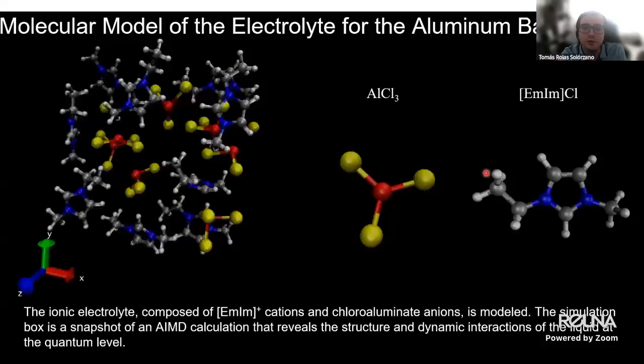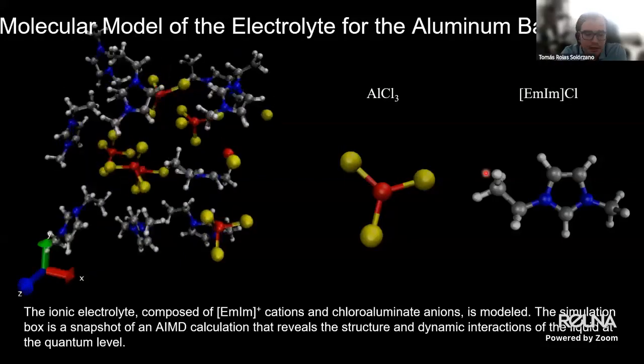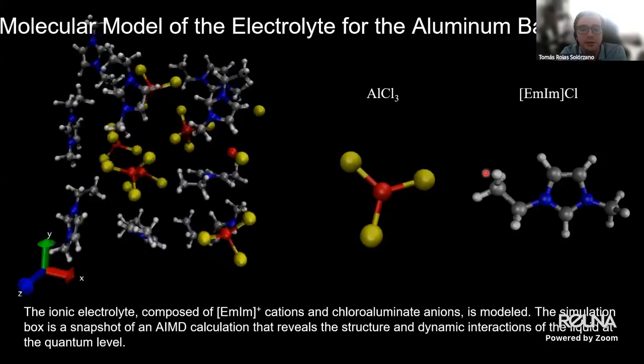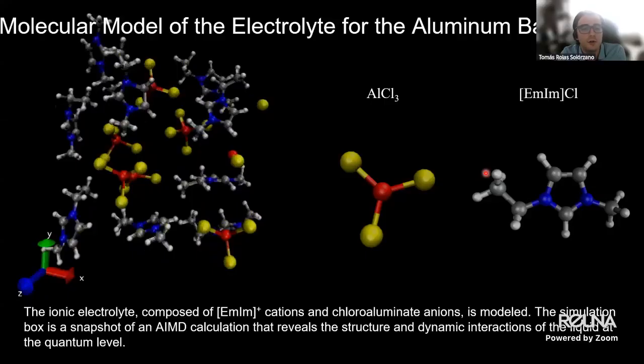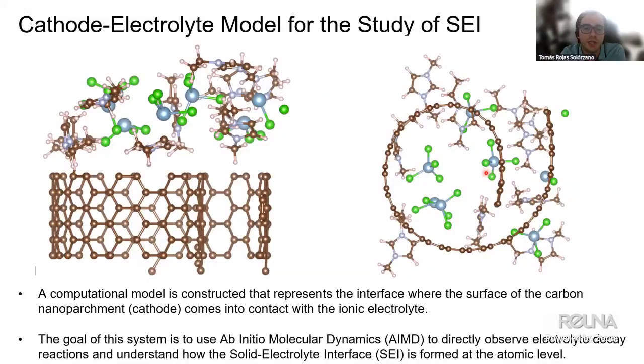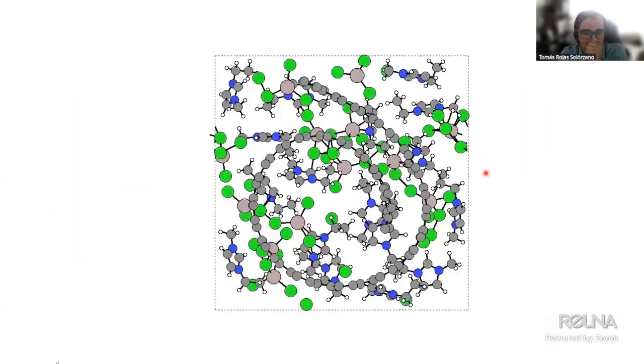Okay, we also do modeling of the electrolyte. I'm going to try to speed up a little bit. And moreover, we do a full simulation of the electrolyte plus a carbon nanoscroll as a cathode of the system. We do this with ab initio molecular dynamics, trying to see, again, the formation of the SEI. And what we can observe here